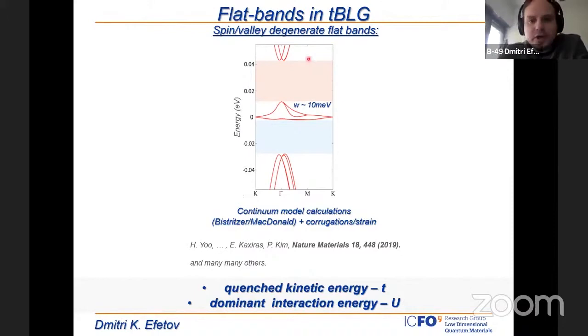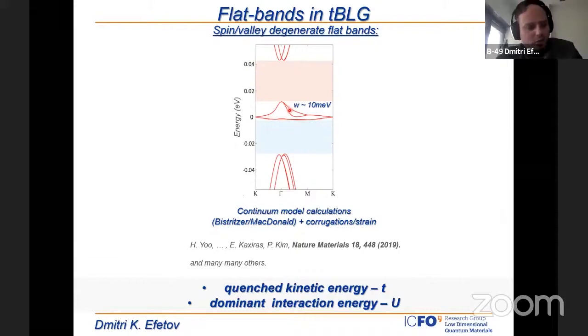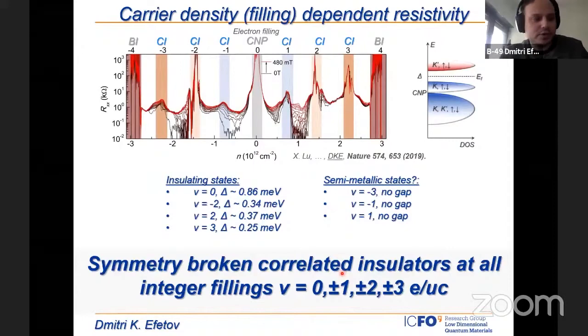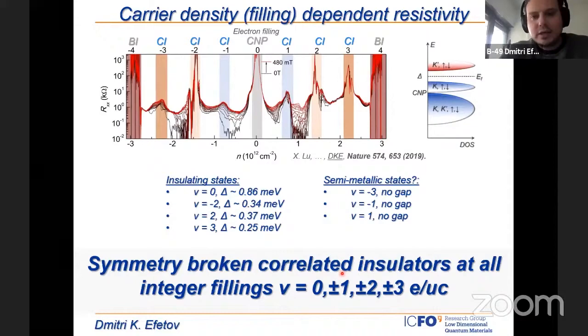These flat bands are really the centerpiece of the physics we study here. For the ongoing talk, we assume our system to be one which has ultra-flat bands around charge neutrality, around energy zero. These bands are around 10 meV in width. Because of the narrow bandwidth, the kinetic energy is extremely low — the electrons almost stop moving in the system. Therefore, the dominant energy scale here is the electron-electron interaction.